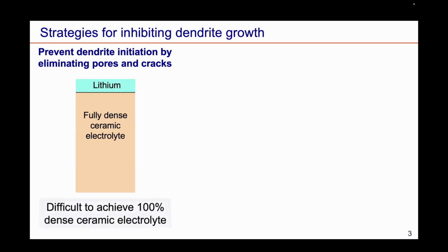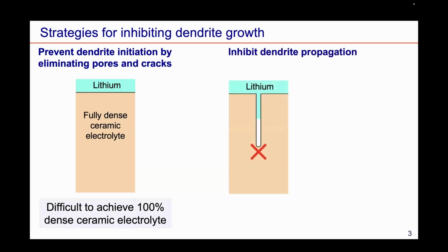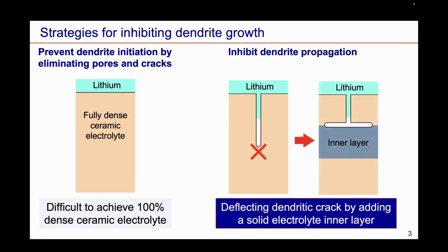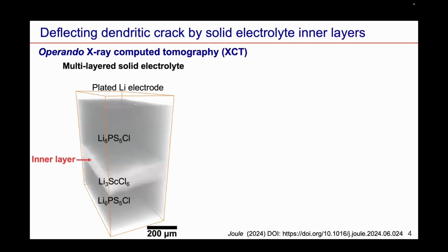However, in practical manufacturing, it is very difficult to realize a 100% dense ceramic. So if we cannot avoid dendrite initiation, we can still prevent battery short circuit by preventing dendrite propagation. One effective strategy is to deflect the dendritic crack by adding an inner layer electrolyte. To prove this, we designed a three-layered electrolyte structure by adding an inner layer ceramic, lithium scandium chloride, in the main solid electrolyte, which is a sulfide-type lithium phosphorus sulfur chlorine, or LPSC, electrolyte.